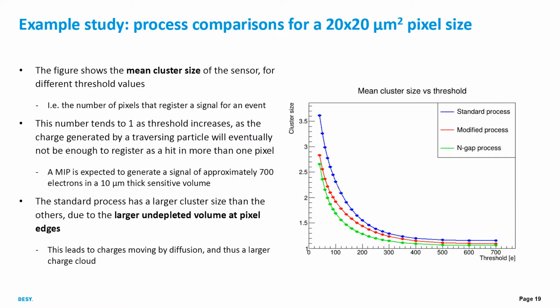Now, we also looked at the cluster size for this. So this figure shows the mean cluster size on the y-axis and the threshold on the x-axis. And what happens here is the cluster size tends to 1 as threshold increases, and this is due to the charge being generated by traversing particle and not being enough to generate hits in more than 1 pixel eventually.